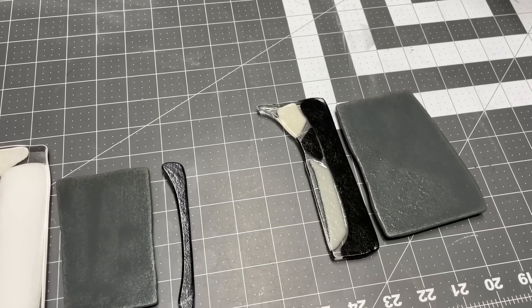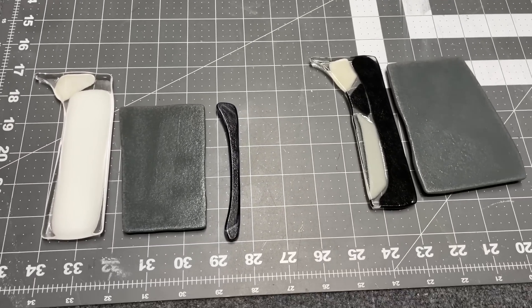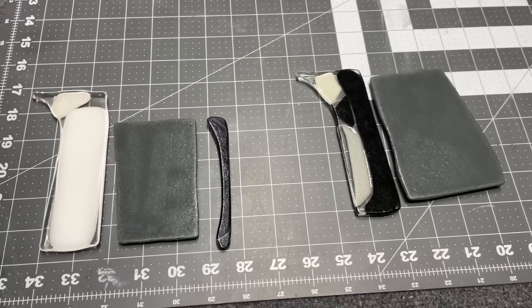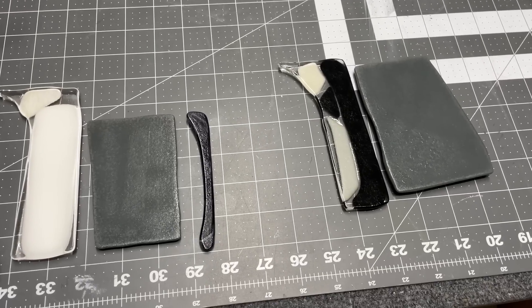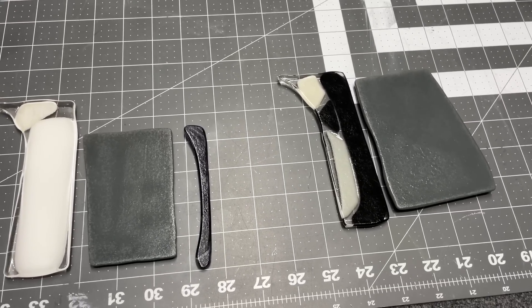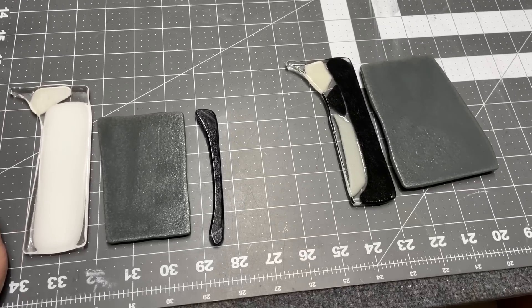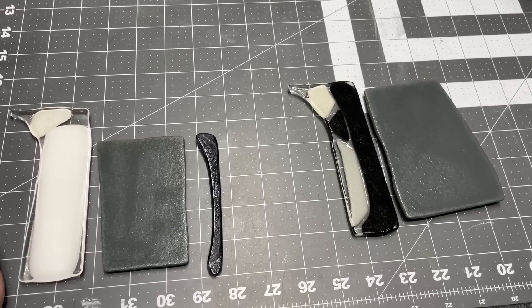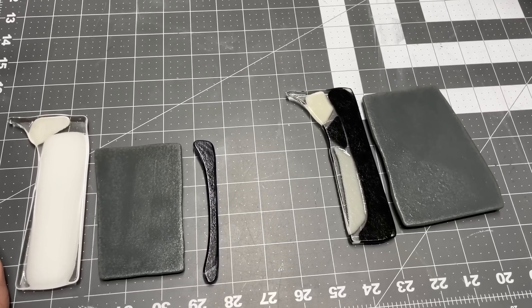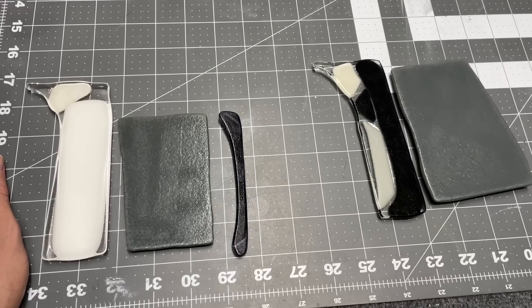I took the opal paper out of the kiln — there's no point in refiring it again, it was decimated. I'm stopping there with those, but I'm going to continue firing the transparent pieces on that same paper. Going in for another firing — this time hotter, because I have other projects going in. These last two firings went to 1465°F for 10 minutes; I'm going to crank that up to probably 1480°F for 15 minutes. We'll see what happens to the transparent after that next firing.